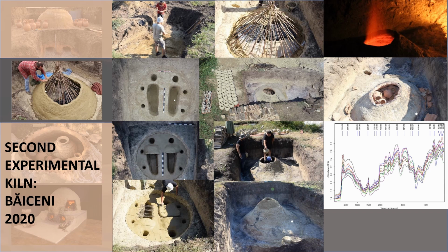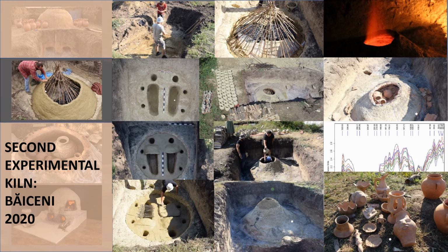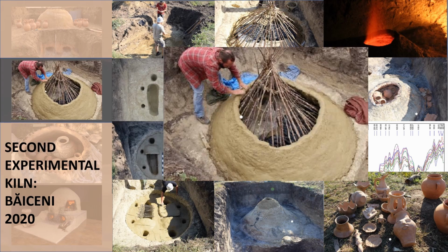The success of this firing reinforced the importance of kiln ventilation in prehistoric ceramic production. The results confirmed that Cucuteni potters were actively experimenting with design features to optimize heat efficiency, providing a compelling example of ancient technological ingenuity. However, research still sought to push firing temperatures to 900 degrees Celsius, prompting the planning of a third experiment.